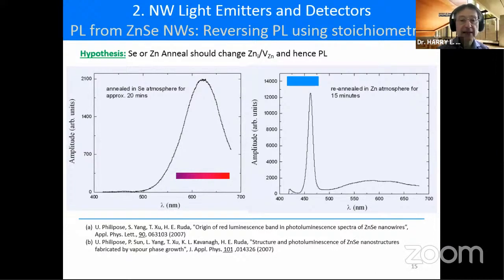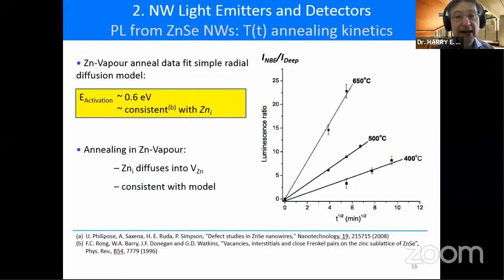And if we take that same wire again and re-anneal it in zinc, we would lose the deep level emission, and we would regain the blue emission. So it's totally reversible. And clearly there's movement of native defects in this Frenkel equilibrium. And so in order to put some meat on the bones, as we say,